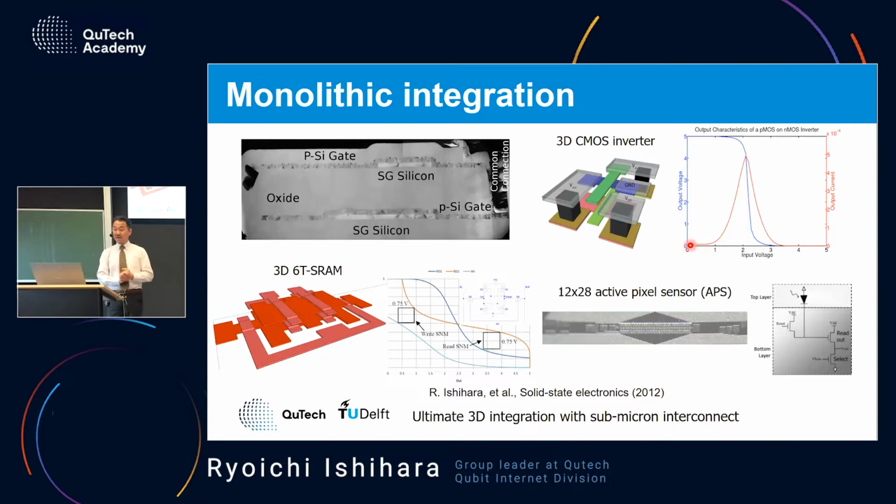The other technology is so-called monolithic integration, and this is the ultimate technology. Instead of stacking chips or layers, this technology just keeps fabricating layers on top of each other, so there are unlimited layers you can stack. In the past, we have shown that we can grow high quality silicon layers by laser crystallization, and we have demonstrated 3D CMOS and 3D SRAM, and we also demonstrated an image sensor,